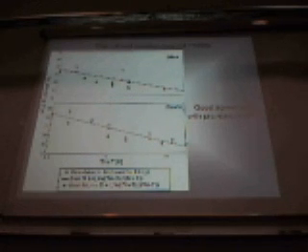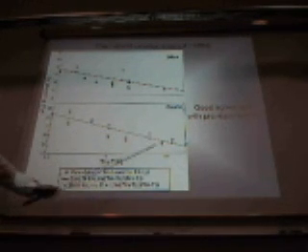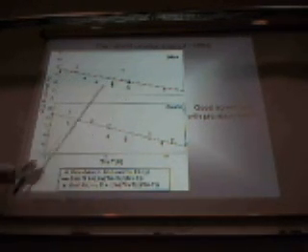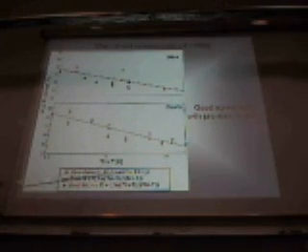And then of course you can, in a linear fashion, correct for this and take the growth laws which we had before, these were the other experiments which I showed you, and correct for this with a linear term, and then you see that they fall relatively close, or close enough, to this logarithmic growth law as they should. So that means there's a second way, or third way, to trigger melting. One is pressure, the other one is thermal, and the third one is radiation damage.